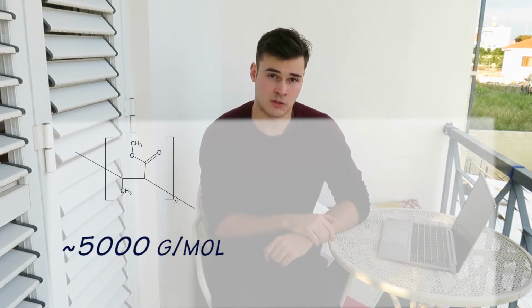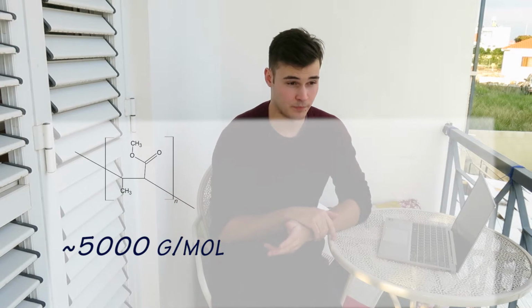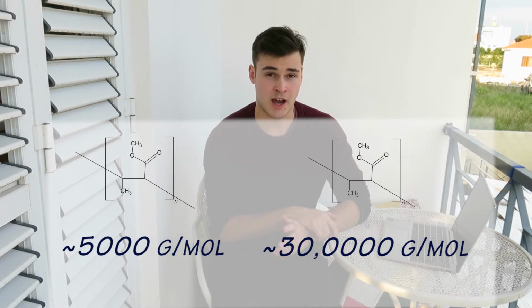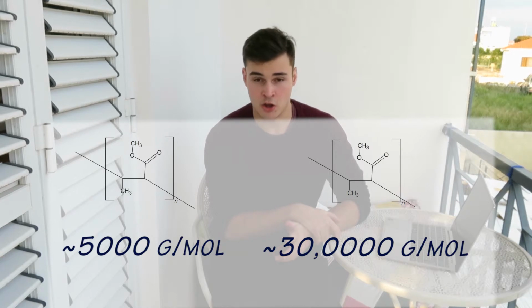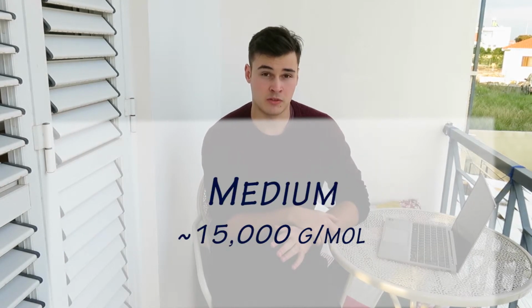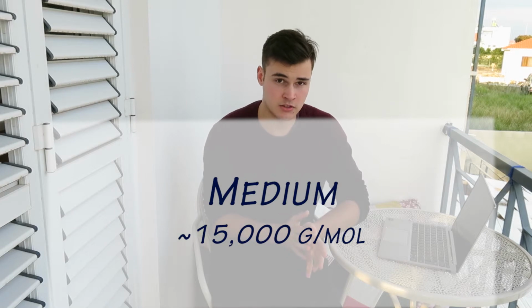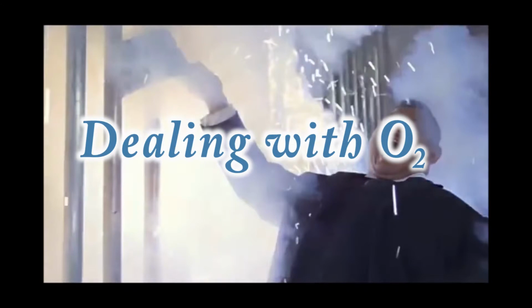If we investigate the activity of the radical polymer chains, we notice that the short chains are the most active, and hence their concentration based on the steady state assumption is very low. Long chains, due to the high mass, are quite inert. This leaves the medium chains with the highest ratio of abundance to activity, leading to them being the most susceptible to attack by oxygen. Since the medium length chains get attacked by the oxygen and the polymerization process is not finished, it leads to a soft and sticky finish on the material, and who wants that?